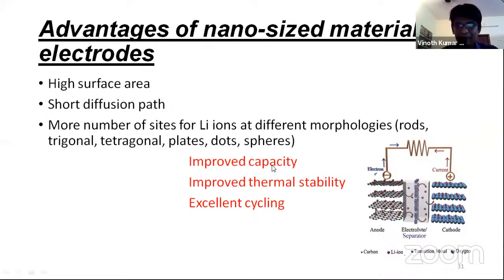For example, improved capacity, in the sense that when we use bulk lithium materials, the capacity will be around 140 milliamp hour per gram, whereas when we go for nanomaterials, the capacity will increase up to 200 milliamp hour per gram. And improved thermal stability, in the sense that usually the thermal stability lasts up to 280 degrees, whereas with nanomaterials, the thermal stability increases up to 300 or 320. And this provides excellent cycling. For example, if the bulk material gives around 1000 cycles, when we use nanomaterials, the cycling rate will be improved by twice or thrice.